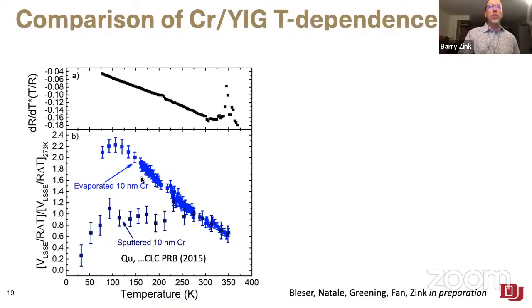So we can also look at essentially the dR/dT, the change in the resistance as a function of temperature of our chromium strip. This is a common trick when you don't have any other way to try to measure whether there's some magnetic transition happening in a material, right? You can see, well, are there any little blips in this? We see two clearly resolvable blips in this dR/dT in our 10 nanometer thick evaporated chromium film.